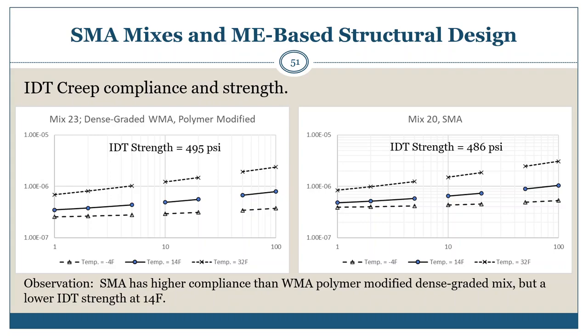SMA mixtures generally have higher compliance than conventional dense graded mixtures, but also have a lower indirect tensile strength measured at 14 degrees Fahrenheit. Specifically, the indirect tensile creep compliance values for SMA mixes generally exhibit more compliance because of the higher asphalt binder content and use of fibers. Higher compliance means mixes are more resistant to thermal fracture.